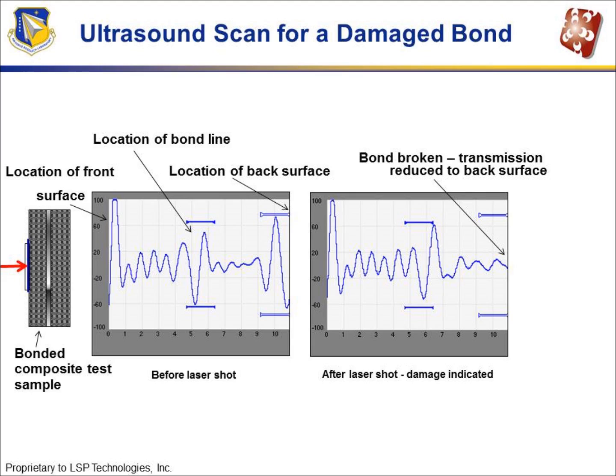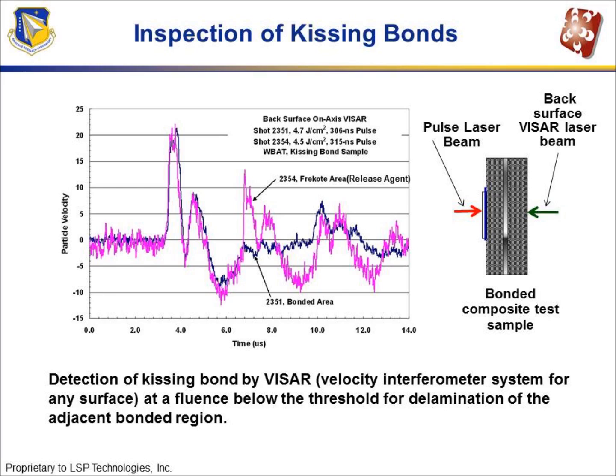This is an example of a VISAR measuring the surface velocity, the back surface velocity of a composite material. Again, we have our normal test setup with the laser beam and the overlays looking at the bond line. The beam is weak enough that it does not affect the bond line. This is an indication of the back surface velocity as a function of time. This is similar to the graph that I showed you before about the simulation. This blue indicates the case in which we have no damage and there's no kissing bond. You can see that has no damage.